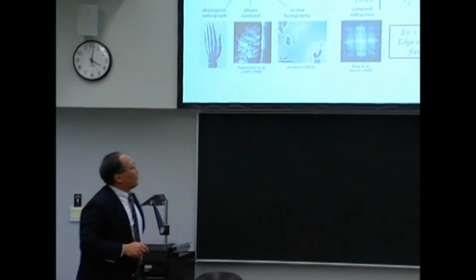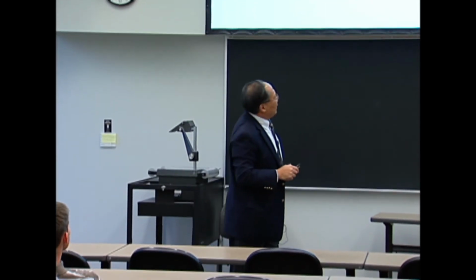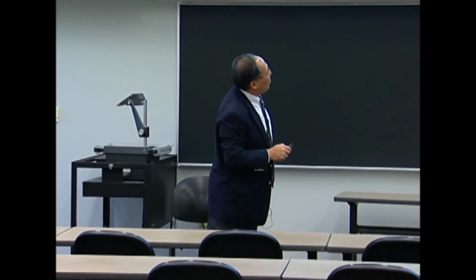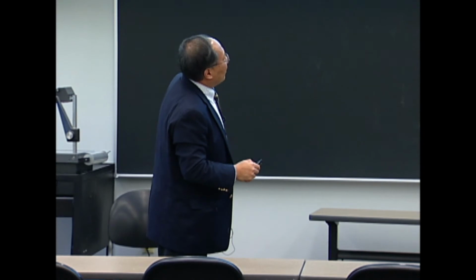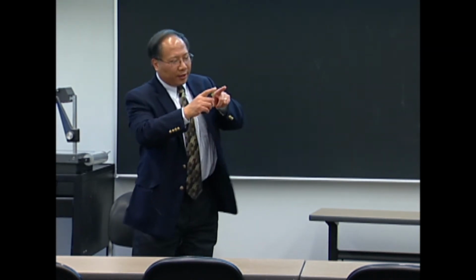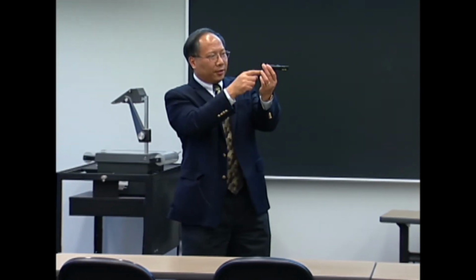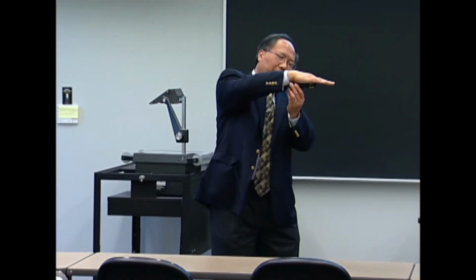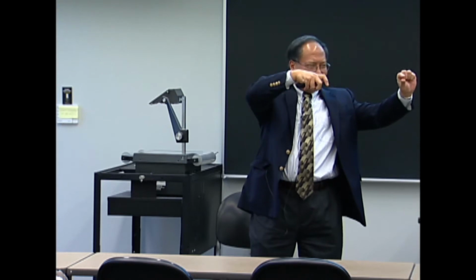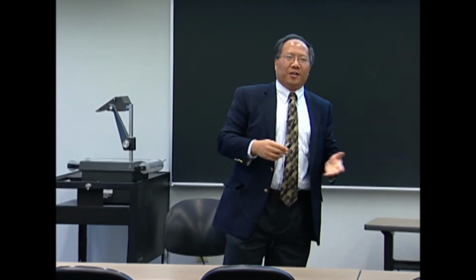For the increase in the contrast, we don't really put our image plane right next to the sample as you have in your dentist office. We take images away from the sample, give it some distance. So if X-ray goes through two faces of the materials, as they propagate, the faces are going to interfere with each other. After distance, you see a little bit of thickness of the interface that initially has a zero thickness. And that's how you increase the contrast.